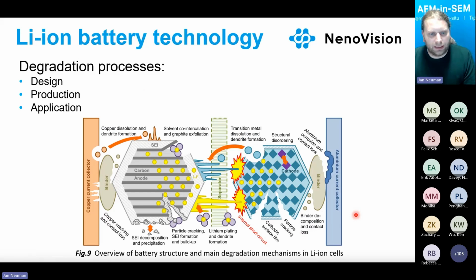There are several possible ways how batteries can degrade, from the particle point of view, like particle cracking, SEI formation, some dendrite formation, and loss of connection between the binders. And all of them we can see by, for example, SEM or by AFM. So that's all from my side, and I will give you the floor to Hansa.